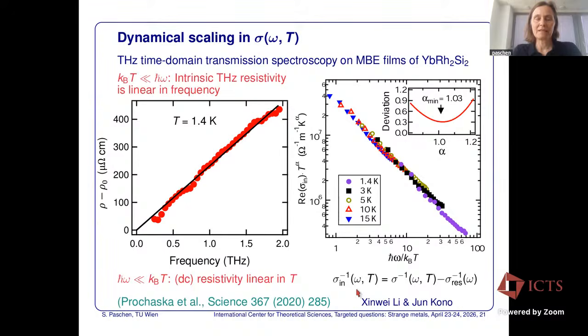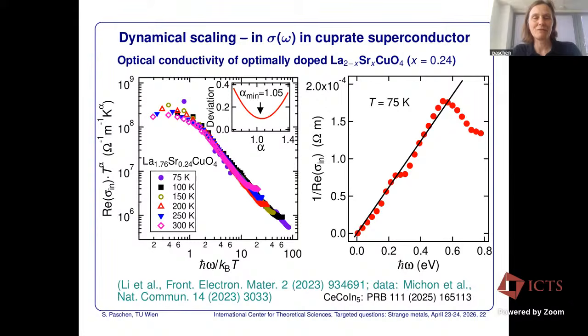I have to stress that this is for an inelastic optical conductivity, so we had to subtract a residual, even though the scaling was almost as good as without the subtraction, but we were alerted to the need for doing this by one of our reviewers. And then we took that approach over to the beautiful data we already saw yesterday on LSCO. And when we also use that same analysis, we here means Xinwei Li from the group of Jun Kono, we actually did this analysis, then a very similar scaling could be found here. And I'm sure you have many comments on it, and also that linear in frequency dependence is directly seen at the lowest temperatures that were available in this study.